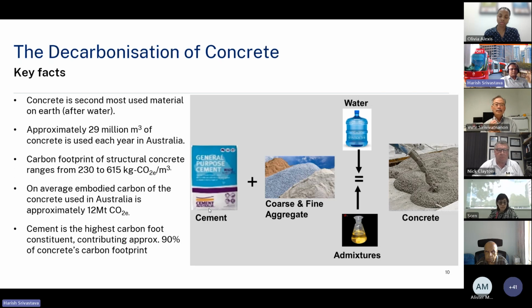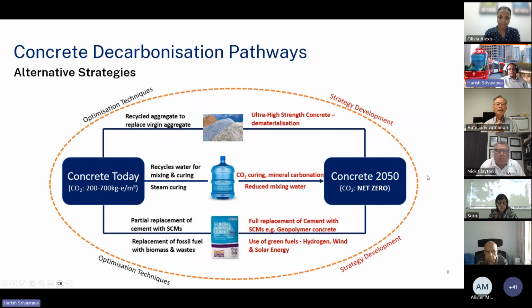With this background, this is my version of breaking down the VDZ report. When I thought about it, I asked what we are doing and what additional we can do. If we start from bottom to top, first is cement. Most of the cement emission is related to process CO2 and fuel CO2. Fuel CO2 is about 26%. What is currently being done is mostly using alternative fuels drawn from waste stream material. Where we need to go, we probably need to inject more and more greener fuels, hydrogen, wind, solar, and probably ethanol could be another addition to this stream.